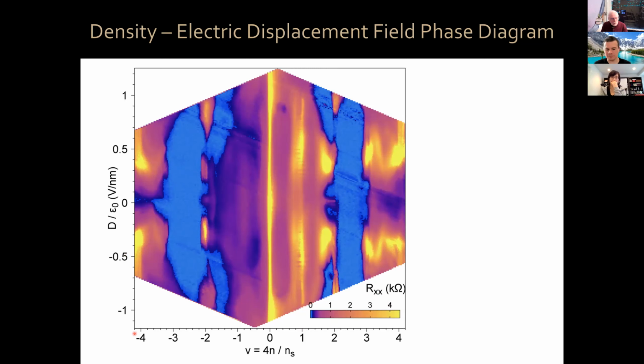Again, from -4 to +4, so from 4 holes per moiré unit cell to 4 electrons per moiré unit cell, and as a function also of the displacement electric field applied in the perpendicular direction. Now this is a pretty complex phase diagram. Let me guide you through it. These light blue regions are regions of superconductivity. You can see superconductivity appears mostly between filling factors 2 and 3, and -2 and -3, but you have also these other superconducting branches.